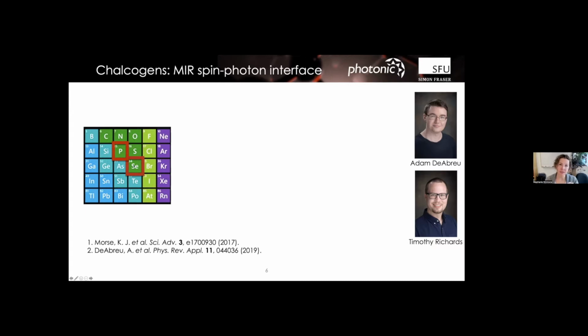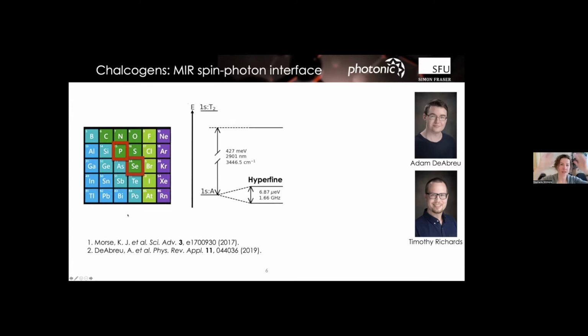If you instead substitutionalize selenium or sulfur or tellurium, they form a so-called double donor, which means that you usually get 2 additional electrons compared to the background lattice. But you can ionize it. You can set your Fermi level, or you can play with charge states to ionize that selenium. And an ionized selenium sure looks like a hydrogen atom, right? So the picture there is that it would have orbital transitions that you could then use. And that's exactly what we found. So it has these 1s, 2s, 2p, you can name them that way. We have some additional structure within that, which gave rise to these relatively strong, but admittedly mid-infrared optical transitions.